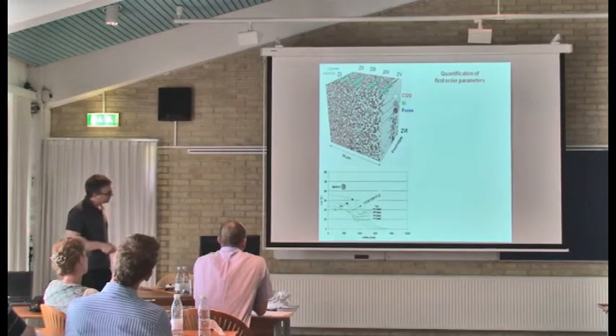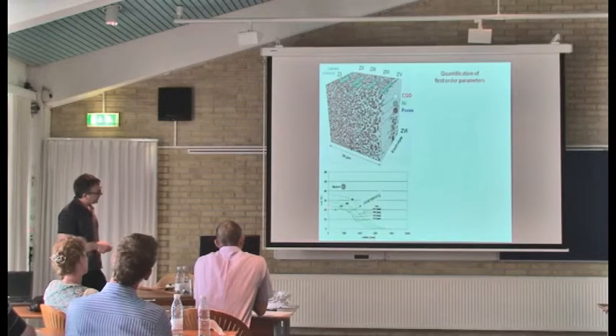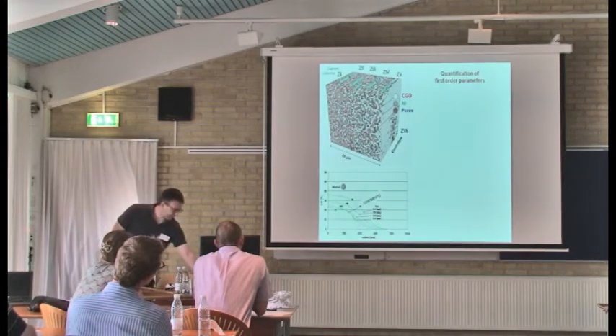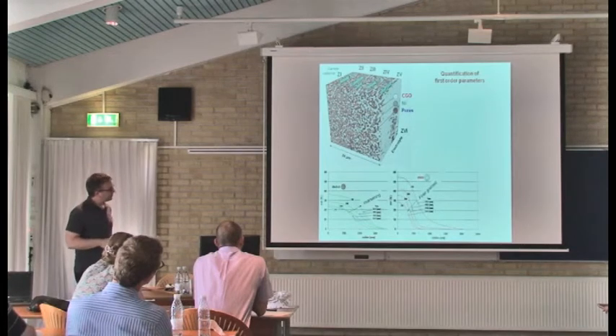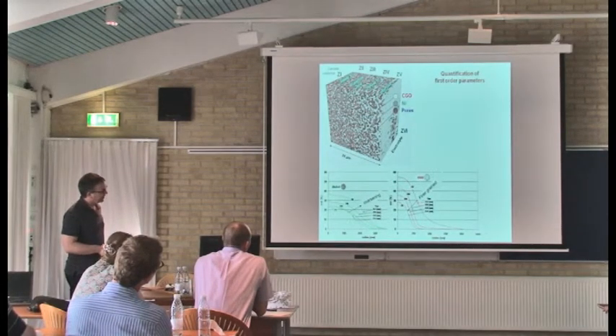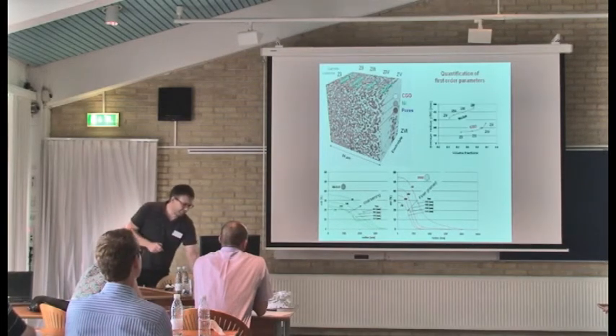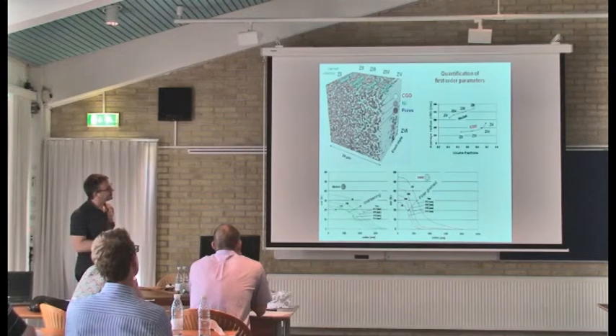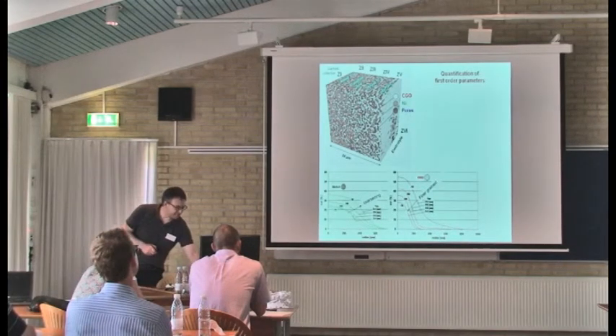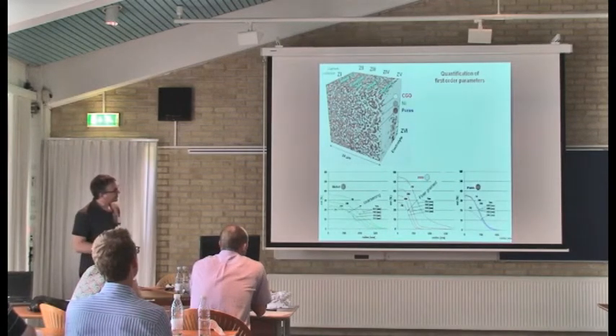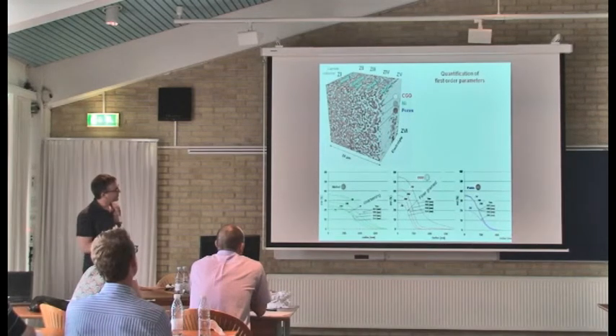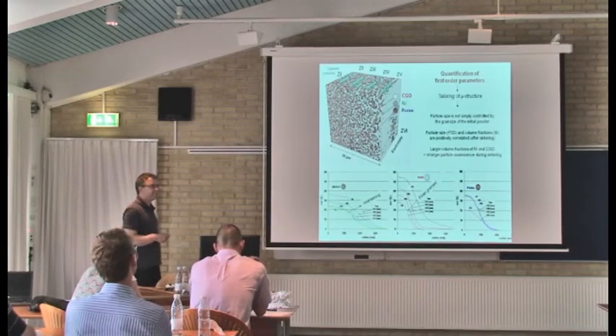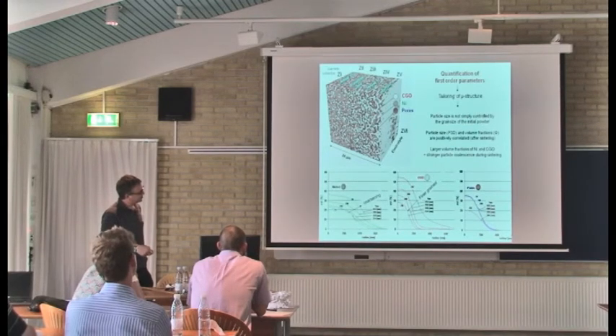We can compare that with cumulative size distribution curves. As the nickel is increasing from here to here, the average size is also increasing. In a complementary way, as the CGO is decreasing, the average size is decreasing. We get, for both phases, the correlation between volume fractions and average particle size. This is not the case for the pore size. The pore size remains quite stable, except at the end we have lower pore size. We were starting with the same powder for the pore size distributions, and this correlation shows us the processing effects.